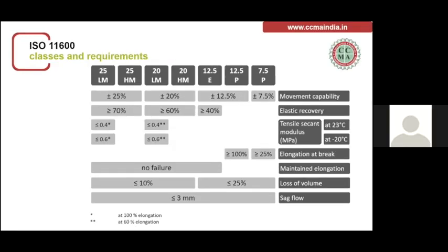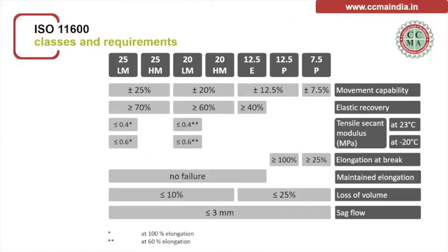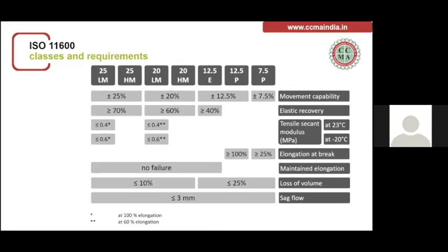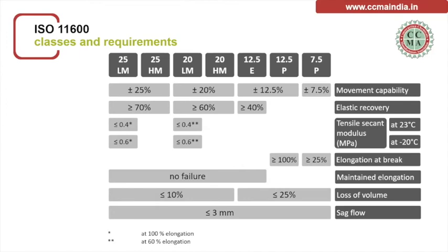The next important property that one needs to look out for is tensile secant modulus. Okay, and this would loosely equate with the hardness of the sealant when it cures. And when the temperature drops, the modulus of the sealant increases. So in case one is selecting a high modulus sealant for a substrate which is very weak, then there is a high chance of failure due to adhesion.